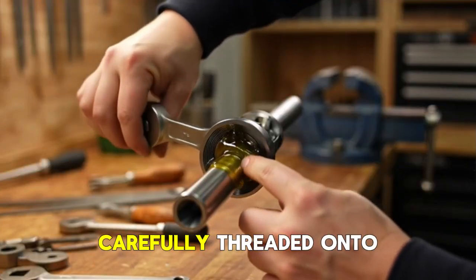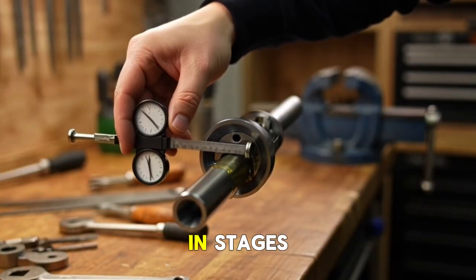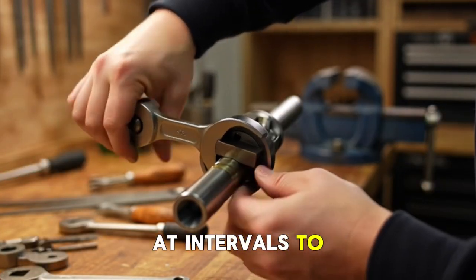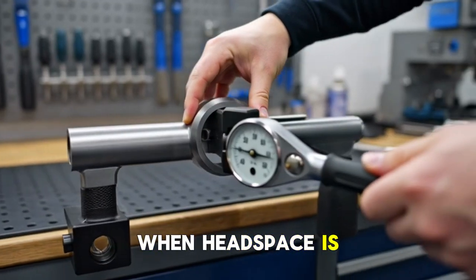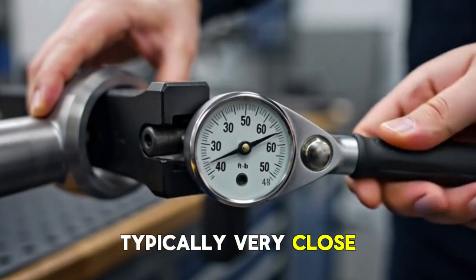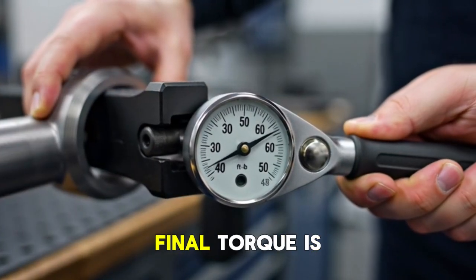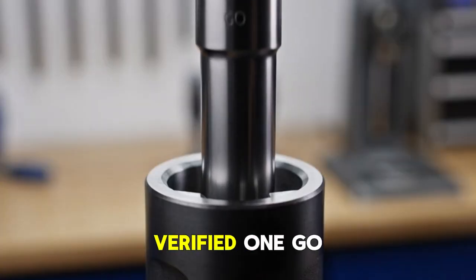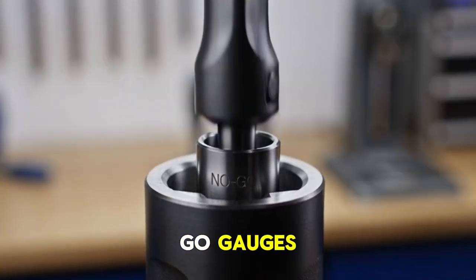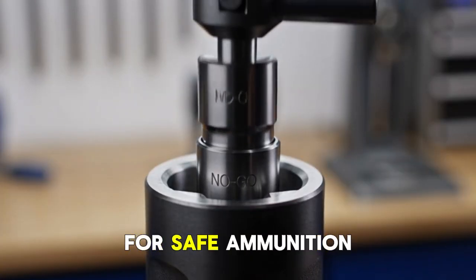The receiver is carefully threaded onto the barrel. The receiver is tightened in stages, with headspace checked at intervals to achieve the target dimension. When headspace is within specification, typically very close to the go gauge dimension, final torque is applied. The bolt is verified on the go gauge but not on the no-go gauges, confirming proper clearance for safe ammunition use.